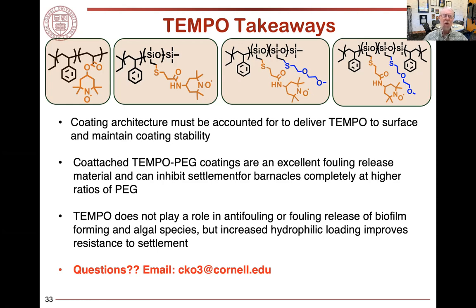So, but let me try to summarize. You can see we've had to march through different architectures. We've done this because the TEMPO itself is extremely hydrophobic, and yet we have to introduce its wonderful functionality into the surface region. And when you do that by coupling PEG and TEMPO together in the same component, the more PEG, the better, but we need to build a robust coating. And so we need to use an ABA triblock material.